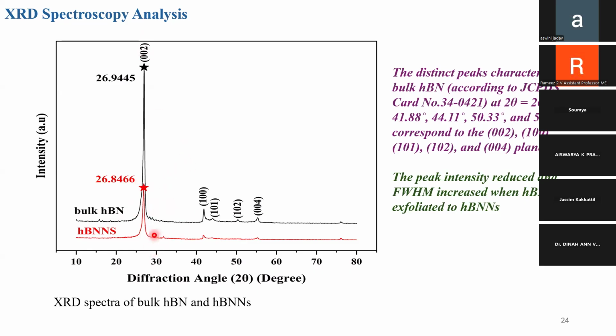You can see a sharp peak at 26.93, which indicates the 002 plane, and nearly at that 26.9 itself, HBNNS is showing. Okay, the 002 plane. So only a 0.1 difference is showing between HBNNS and bulk HBN. That itself proves that the synthesized HBNNS has preserved the crystallinity, the crystal structure, even though it was synthesized with a particular method.